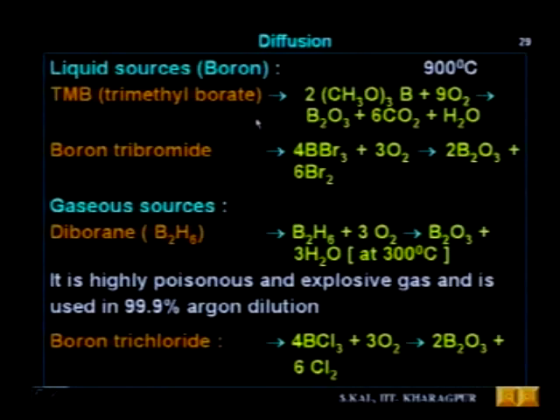So these are all the boron sources and their reactions, and we found that whatever the source is, solid, liquid or gas, in all cases the first reaction forms B2O3, boron trioxide, and after boron trioxide is formed, it reacts with silicon and forms the individual boron atom and silicon dioxide. The boron and silicon dioxide together sometimes form boron stain or skin, and that is removed before drive-in diffusion by converting the boron skin completely into borosilicate glass, which is done by low temperature oxidation, known as LTO. Okay. Now we will discuss phosphorus as a dopant.